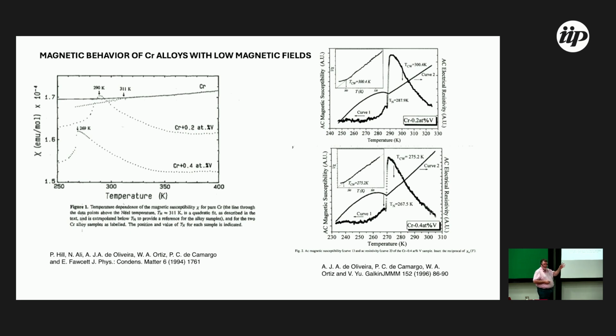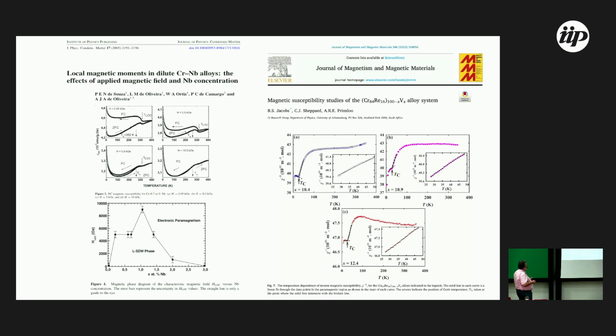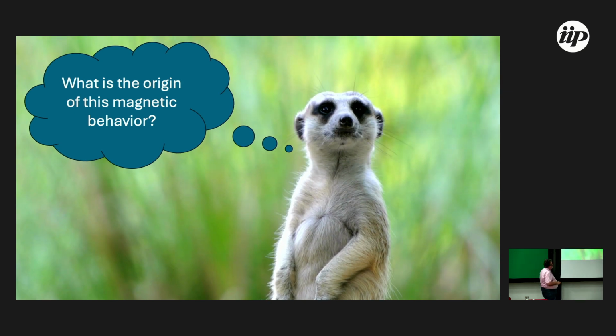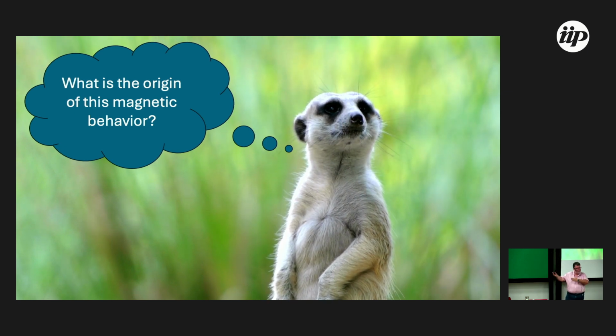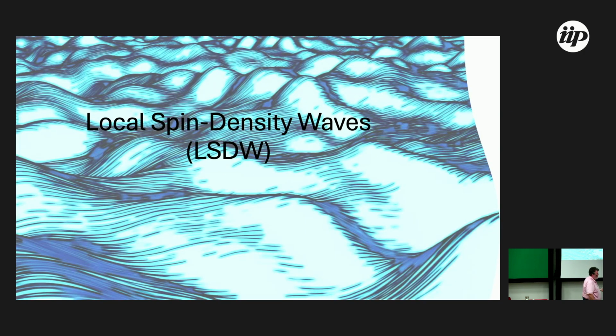This sample is a high quality single crystal, special chromium 0.2, with many neutron and X-ray experiments performed on the same sample, and this behavior is observed. This behavior is also observed in other chromium alloys, for example the chromium-niobium alloy, with the same behavior. And the group in South Africa observed chromium, rhenium, and vanadium alloys, with Curie-Weiss behavior in these samples too. What's the origin of the magnetic behavior? And why was this behavior not observed only in the 90s, but also in the 60s and 70s? Magnetic moments were common at that time.